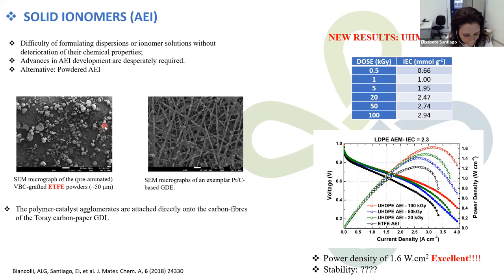So here we started working with ETFE, in a collaboration with Professor John Varco. And we have obtained, you can observe from these images, that the powder is agglomerated and attached directly on the carbon fibers of the Toray carbon paper GDL. So even having very large particles. However, the stability is still a problem. You have a lixiviation of these materials during operation.